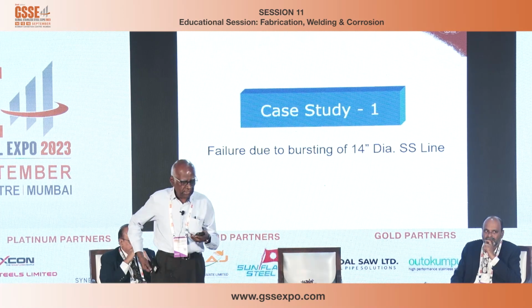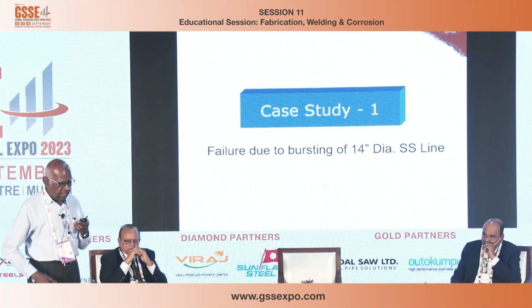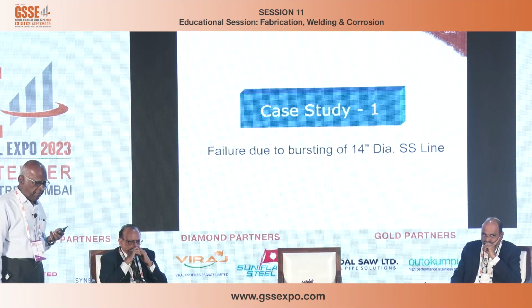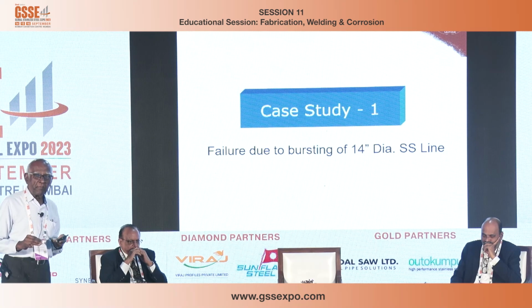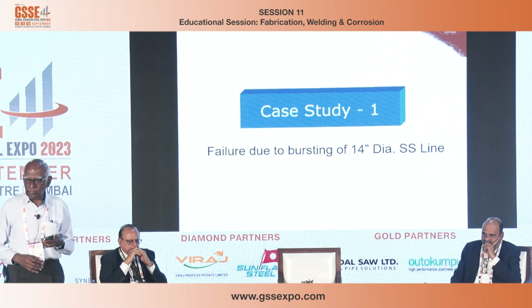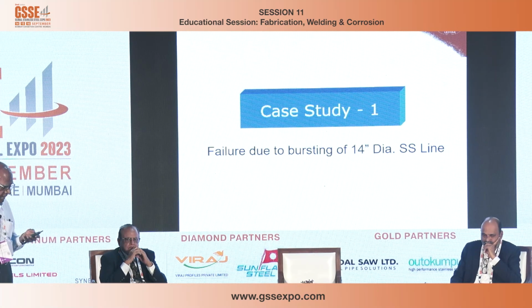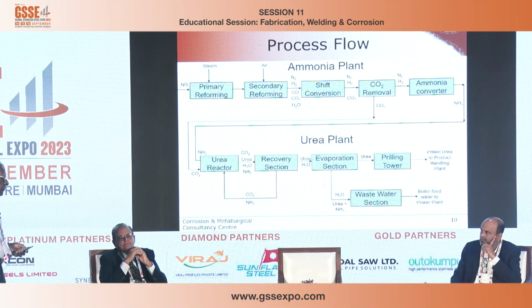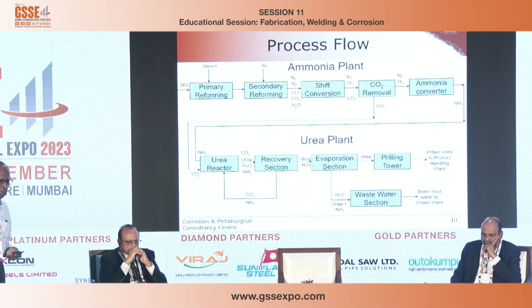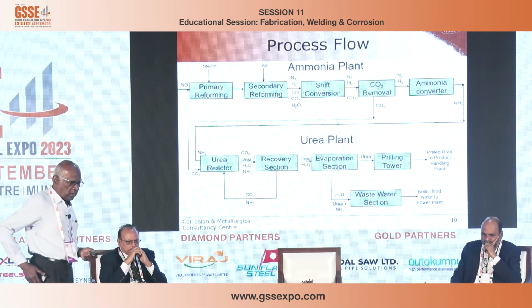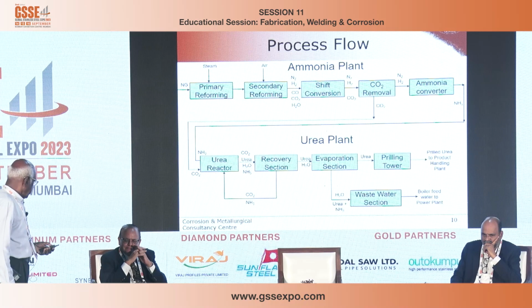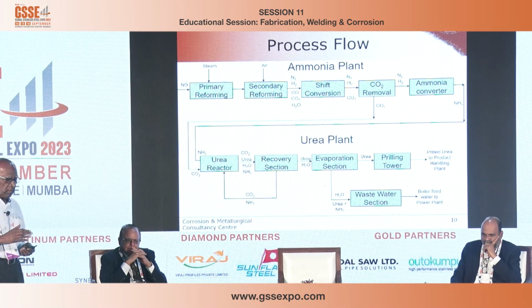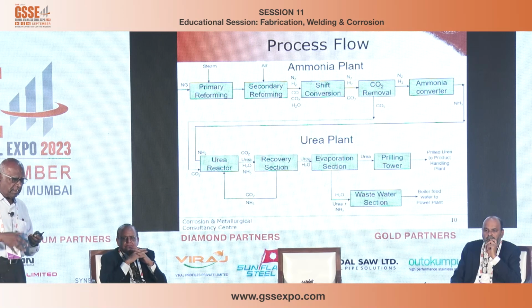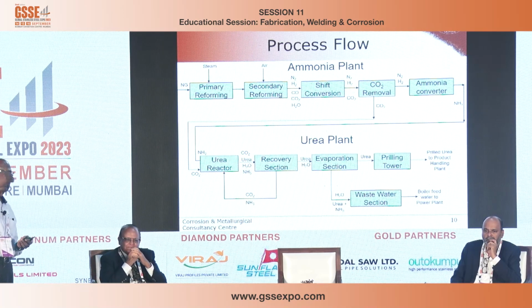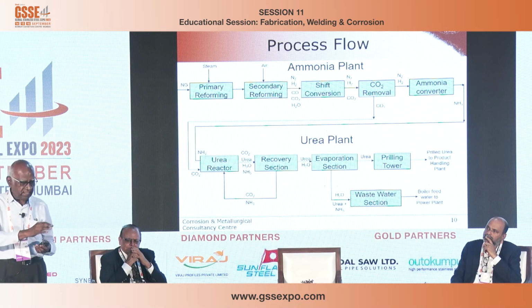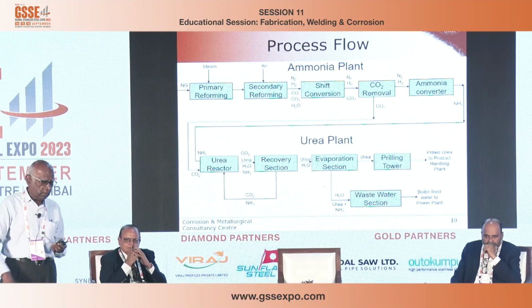This talks about a 14-inch diameter, 8 mm thick stainless steel pipeline, which suddenly failed after a couple of months of service. It was meant for 25 years of service. This is from a fertilizer plant. Urea is made out of ammonia, NH3, and CO2. So you have to remove the CO2. That's why we talk about green nowadays. You have to remove CO2 and send it to the air, and the balance NH3 you react again with CO2 to produce urea.